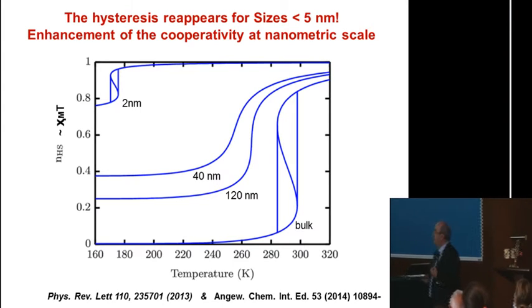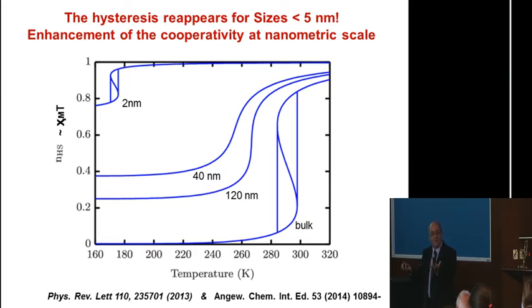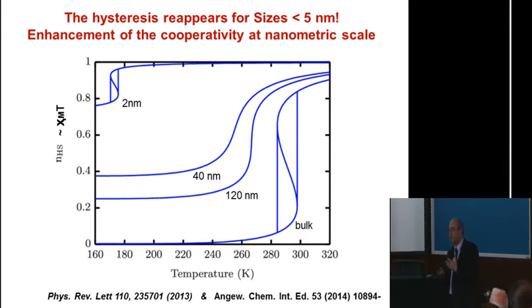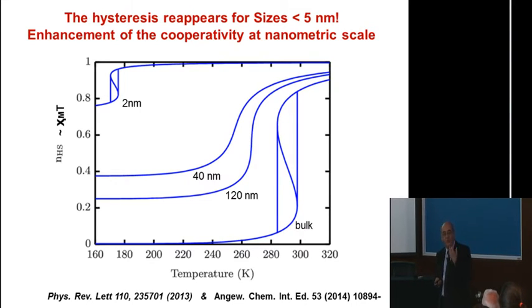And then the idea comes from Mössbauer spectroscopy, where we studied the elasticity of these systems. What we have seen is that the surface may have elasticity which can be a lot higher than the bulk. When we go to very small dimensions, we have the elasticity diverging because of the surface effect. And because the cooperative interactions are elastic, if you have something increasing the elasticity because you have surface effect at very low dimensions, you have only surface here. So then you can make a reappearance of your hysteresis loop. That means that at very low dimensions, 2 nanometers or 1 nanometer, you can have a hysteresis loop. Okay, that means that you can go in your integration to very low dimensions and try to have high density information storage.